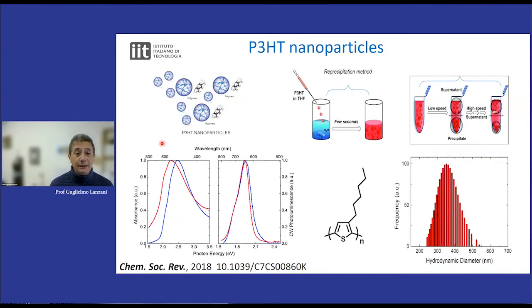The way we produce nanoparticles is the reprecipitation method, in which to a good solvent, you add what is called a bad solvent. So there is a hydrophobic reaction and the polymer escapes the bad solvent. Here it was water. And it starts to aggregate, and by changing the concentration, you can to some extent control the size of the nanoparticles that are obtained. You can get rid of the solvent, which is something not bio-friendly, by centrifugation and filtering, or say dialysis. So as much as possible, we get rid of the solvent and we obtain nanoparticles with a diameter in the order of a few hundred nanometers. It apparently is not so critical, it should be larger than a few hundred.